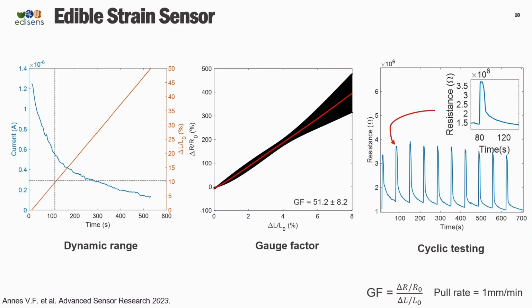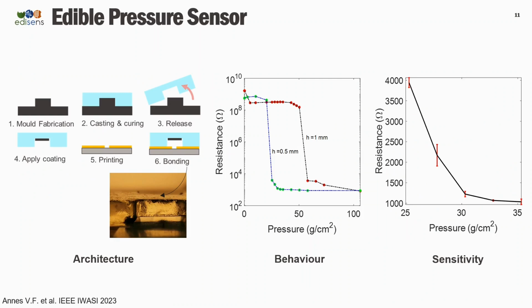And the coating, so we have seen electrical conductivity, we have seen stretchability, so we can use it for a strain sensor. We have used it also for pressure sensing. For pressure sensing, we developed a small gelatin microstructure, mainly by molding. So you have two gold electrodes, and then you have a gelatin architecture using our coating to create a conductive path. So it's pretty much a bistable pressure sensor. When you press this gelatin microstructure, you achieve contact, which of course switches on the sensor. And then as you increase the pressure, the contact area will increase, and the conductivity will go higher.